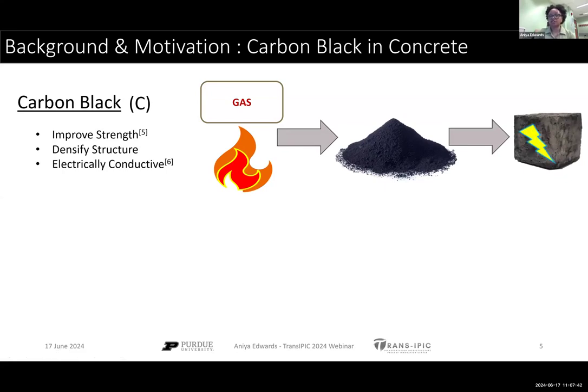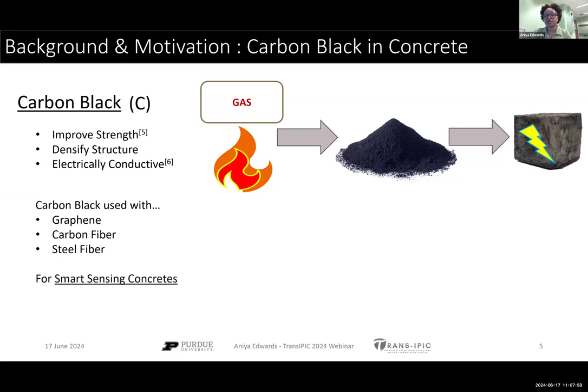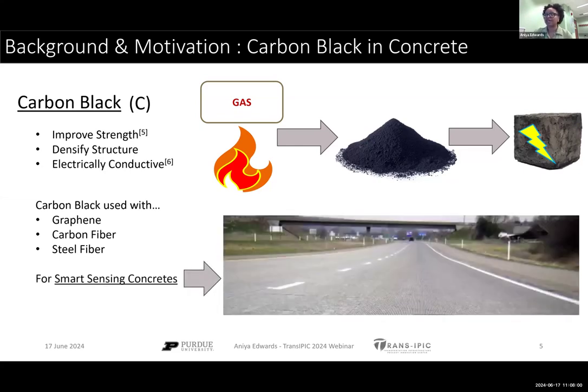Carbon black is shown in different studies to improve strength, densify the structure of the composite, and it can be electrically conductive. In fact, carbon black has been used with graphene, carbon fibers, other steel fibers to create a sort of framework within the cementitious composite. And that can in turn be used for smart sensing concretes. Just last week, there was an article posted on an MIT study where they actually found carbon black to be a sort of supercapacitor that can be used to conduct electricity through a cementitious composite.